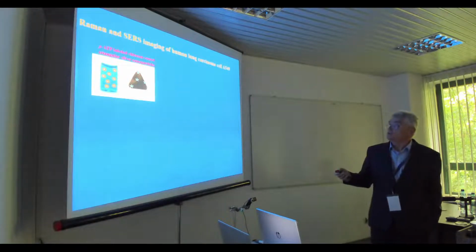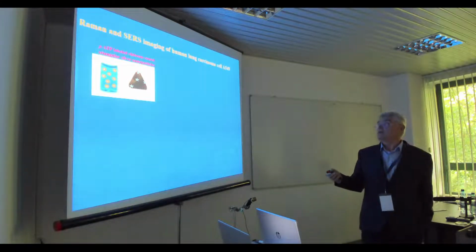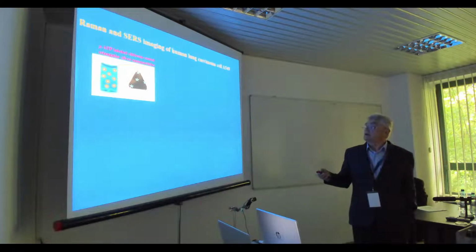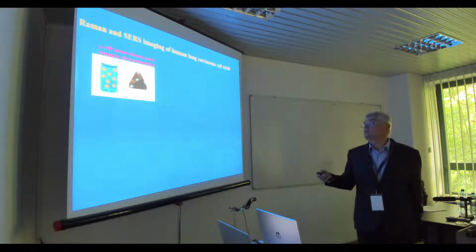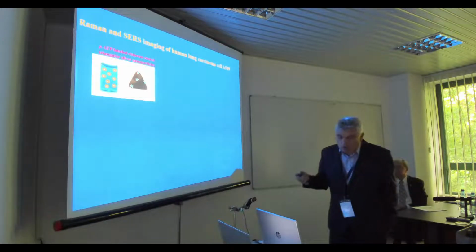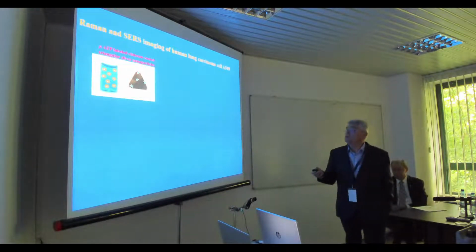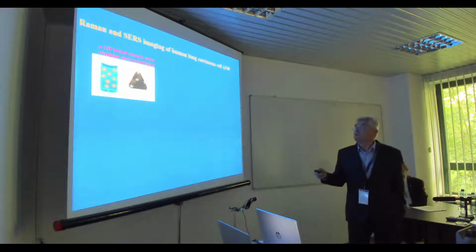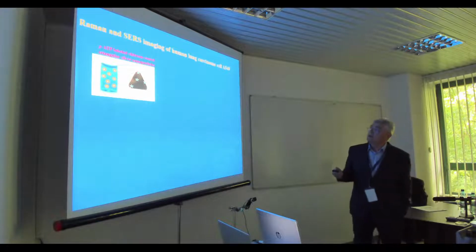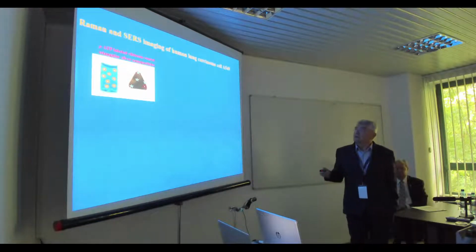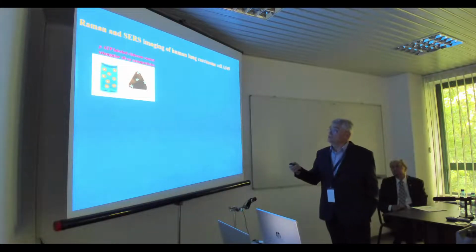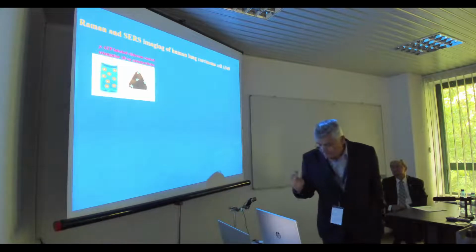So we use triangular because there are several resonances, protected in the chitosan, coated with chitosan, and also attached to the metal is a small molecule, aminothiophenol, which connects by thiol with the metal. So this kind of nanoparticle inside the cell will give the specific signal from para-aminothiophenol with a very few bands and can be easily